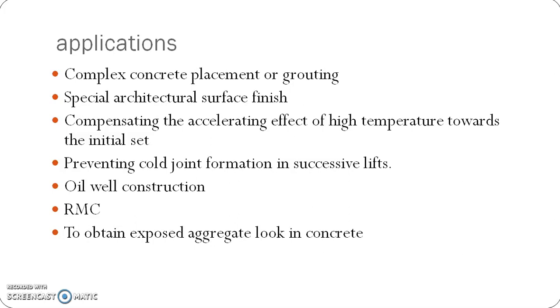Retarding admixtures are sometimes used to obtain the exposed aggregate look in the concrete. So the retarder is sprayed on the surface of the formwork. It prevents the hardening of the matrix at the interface of concrete and formwork, whereas the rest of the concrete will get hardened. On removing the formwork after a day or two, the unhardened matrix can just be washed away and we can get the exposed aggregates. This is for increasing the aesthetic view of a structure.